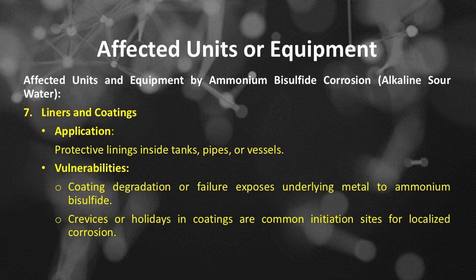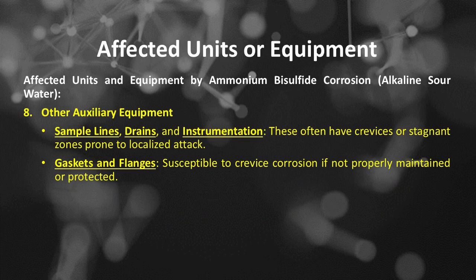Affected units and equipment by ammonium bisulfide corrosion or alkaline sour water. Number 7 is liners and coatings. The application of liners and coatings is protective linings inside tanks, pipes, or vessels. The vulnerabilities include coating degradation or failure, which exposes underlying metal to ammonium bisulfide. Crevices or holidays in coatings are common initiation sites for localized corrosion. Number 8 is other auxiliary equipment: sample lines, drains, and instrumentation.